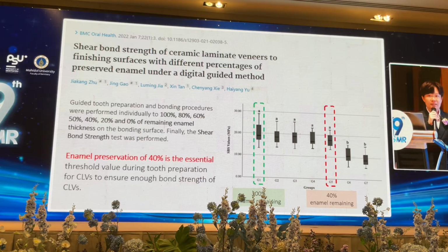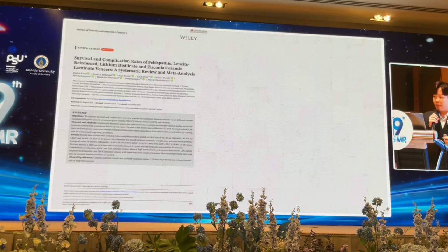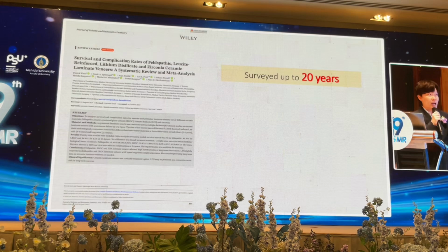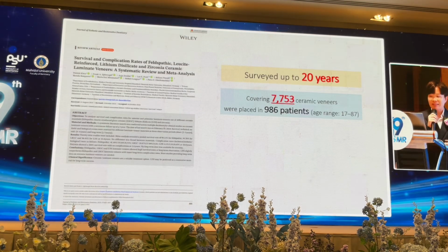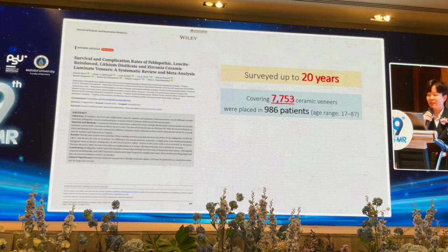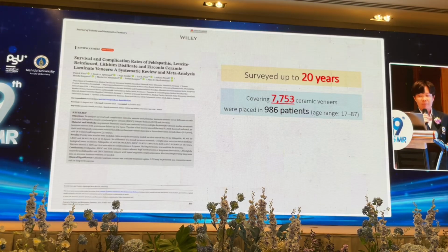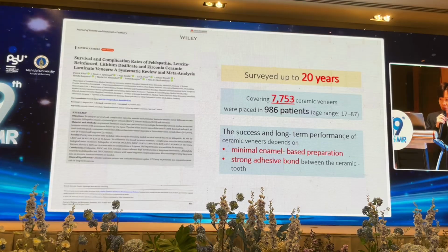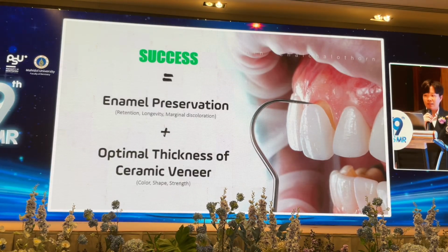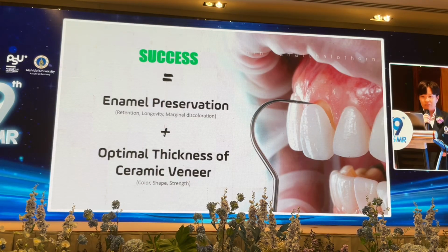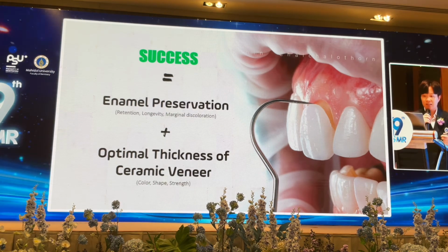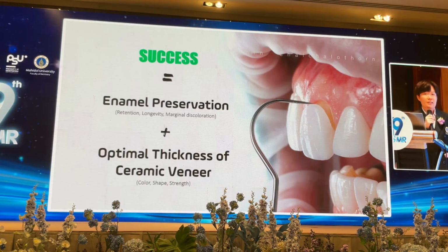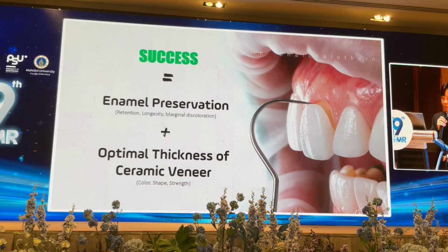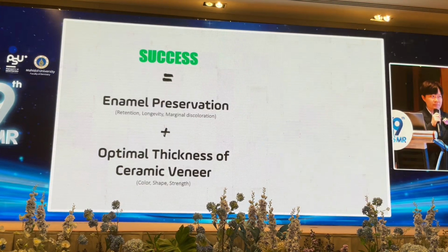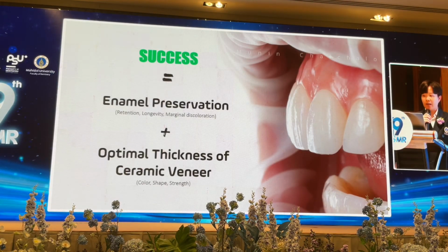of full enamel coverage. And this study is actually a systematic review and meta-analysis that tracked the survival rate of ceramic veneers for up to 20 years, covering more than 7,700 veneers placed in almost 1,000 patients. This found that the long-term success of ceramic veneers relies on two main factors. The first one is minimally invasive, enamel-based preparation, and the other one is a strong adhesive bond between the ceramic and the tooth structure. So I can confidently say that the success of ceramic veneers relies on preserving enamel to ensure good retention, long-term durability, and reduced marginal discoloration, plus optimizing the ceramic thickness to achieve the preferred color, shape, and strength. And if we do it correctly, the outcome should be both beautiful and long-lasting.